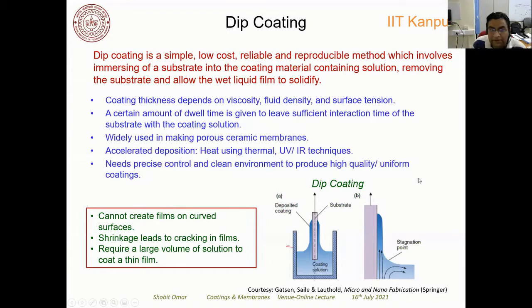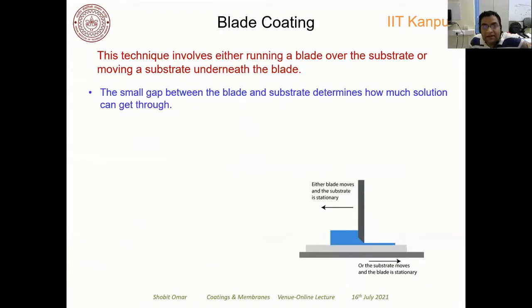Okay. So let's go to another. So this is another type of liquid phase coating technique. It's a blade coating, and in this technique you have a liquid phase and you run the blade over the substrate, and you see there is a gap between the blade and this substrate, and through this gap, the thickness of this liquid coating is decided. Okay, if you want to have a thicker coating, then you keep this gap higher. So the small gap between the blade and substrate determines how much solution can get through.